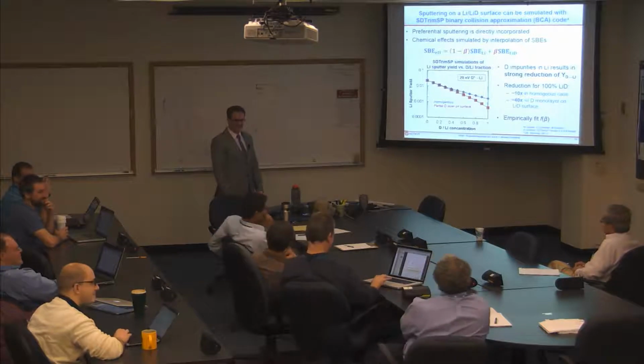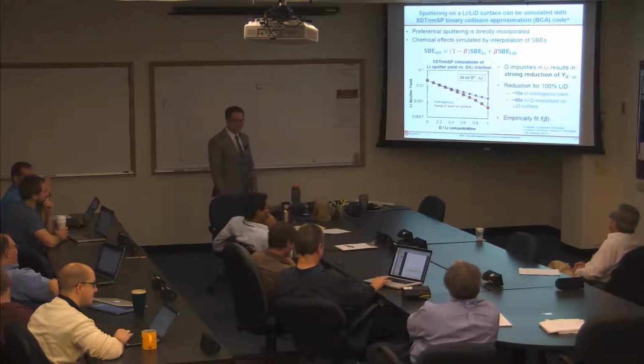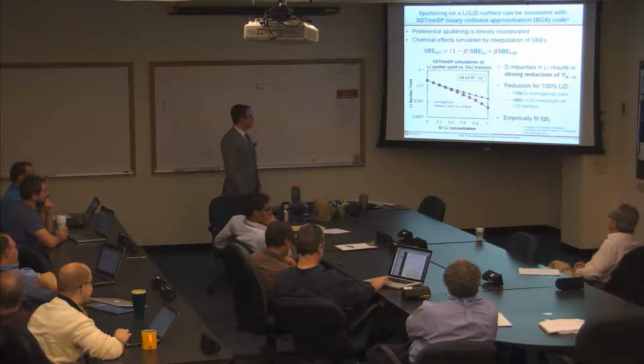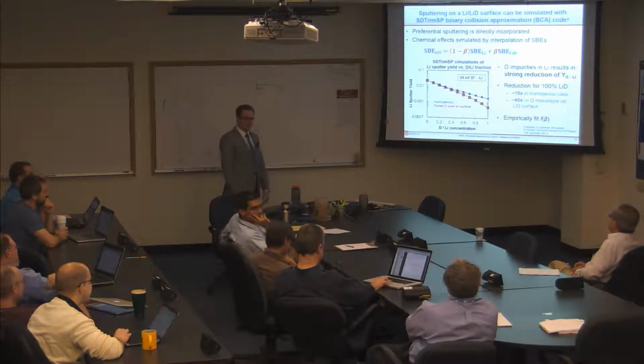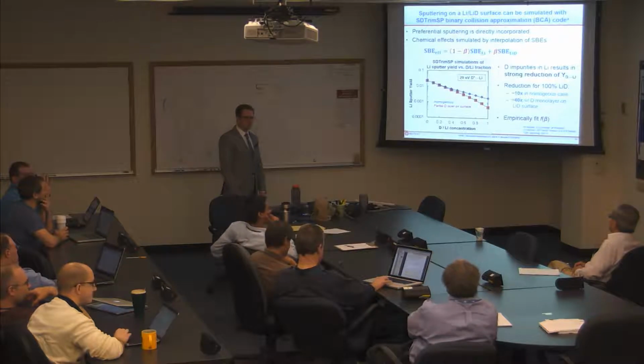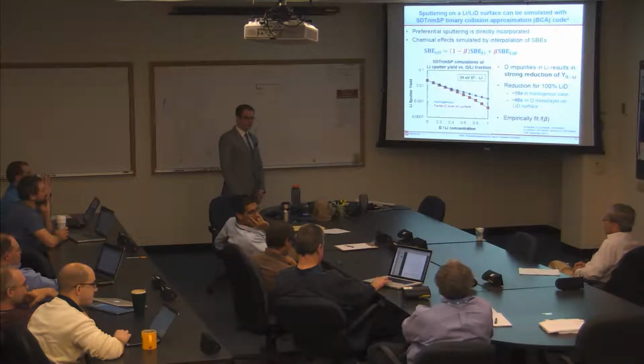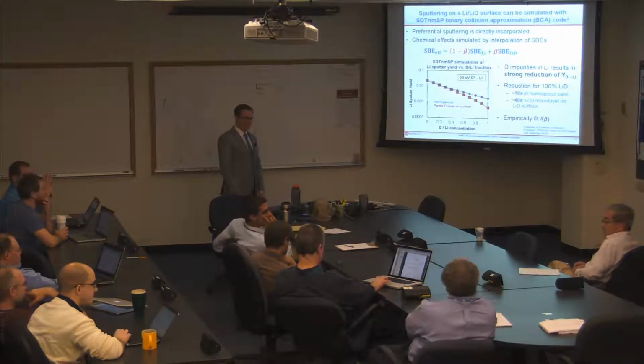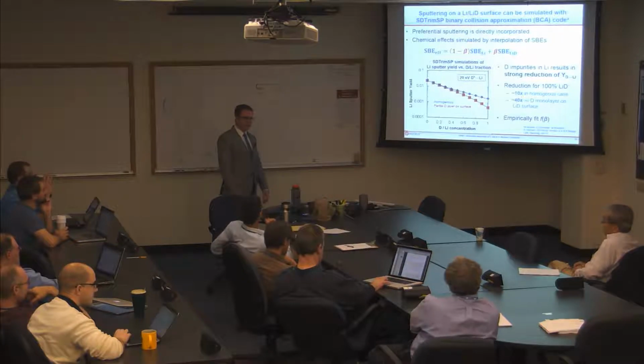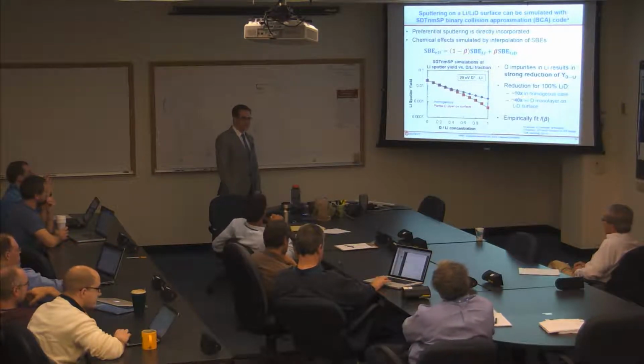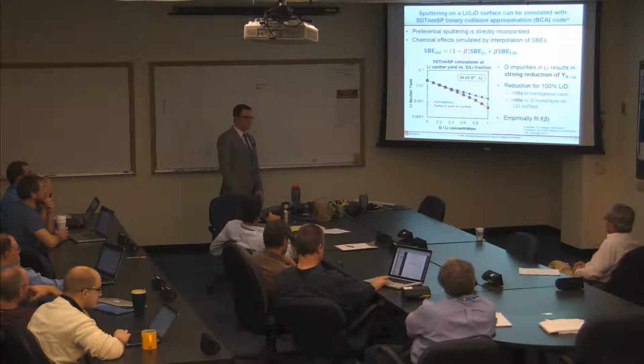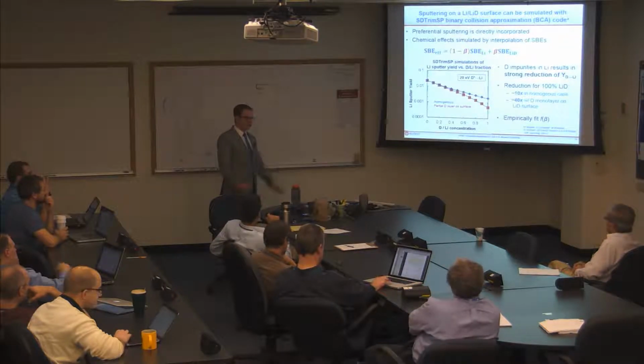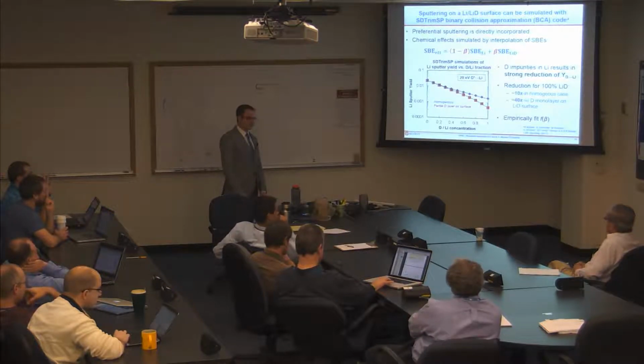So what you're saying is that if they're 50-50, then it's 100% LiD. Yes. And why would you say that? That's the assumption. LiD is 1-to-1. I'm assuming that it all is precipitated as lithium deuteride and not free-flowing lithium and deuterium atoms going around. And there is evidence of that in the MD simulations.